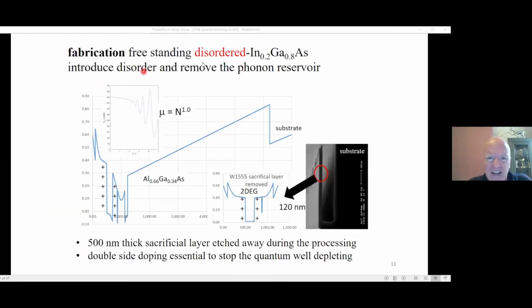So, moving on to how we make these devices, I mentioned that they are freestanding. This is a picture of the conduction band. This is the surface here. This is the InGaAs quantum well here. The little plus signs there are the doping that we put in, the delta doping that adds disorder. So electrons in the quantum well really feel this disorder. The rest of the structure is buffer layers to the quantum well and a very, very thick InGaAs layer. Now this very, very thick InGaAs layer is later removed by etching.